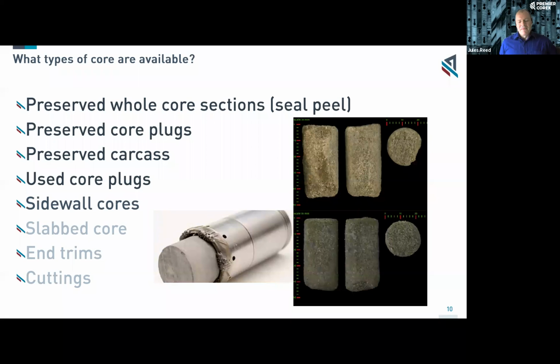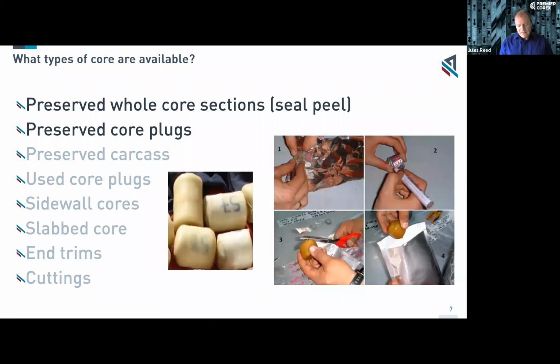I don't know the exact makeup of the wax. The wax that is used these days, which looks like this one here, this light colored wax, is a low temperature wax, so it's liquid at low temperature. So it's much safer. The old waxes used to have to be heated to 180 or 200 degrees. This wax, you can heat at maybe 40, 50 degrees. Part of the reason for using the aluminium foil and then the plastic wrap is to ensure that the wax isn't getting into the sample.